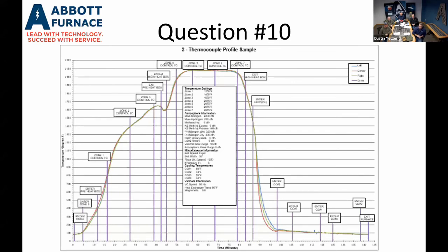The other temperature deviation they're asking about is the deviation in the zone, which is the difference between the process value temperature and your set point temperature. So if I have a zone that's set at 2075, typically the deviation alarms are set about 20 degrees F from set point, plus or minus. If I go below 2075 by 20 degrees, typically the horn fires. The horn will sound, giving you an alarm that says there's a deviation in a certain zone.